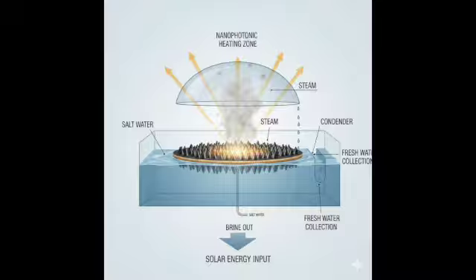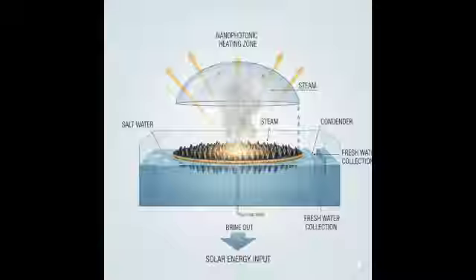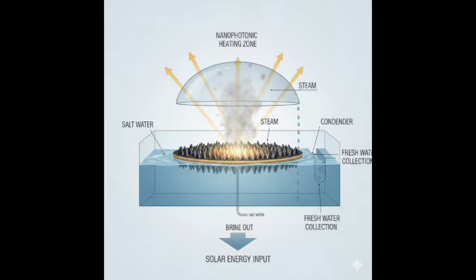However, this structure is used cleverly in some integrated PV-MD devices. Okay, unpack that. Using waste heat from solar panels. Exactly. Solar PV cells get hot during operation, which actually reduces their electrical efficiency. So the idea is to integrate MD channels directly behind the PV cells. So the feed water for the MD cools the back of the PV panel. Right. The waste heat from the PV cell heats the feed water in the first stage of a multi-stage MD system integrated behind it. It's a win-win. You cool the PV cell, boosting its electrical output. Studies show maybe a 4.5% increase. And you get free preheating for your MD process. Correct. A 3-stage PV-MD device using this waste heat reportedly achieved a respectable permeate flux of about 1.79 kg/m²h per sun under standard sunlight conditions. Clever integration.